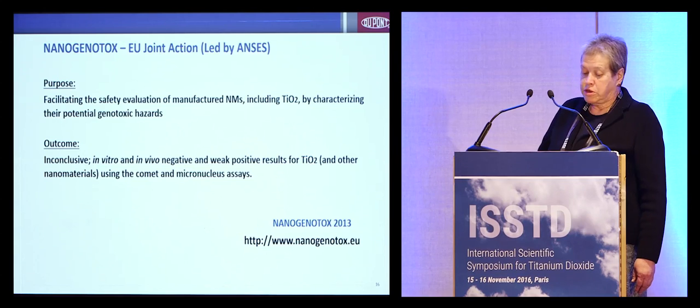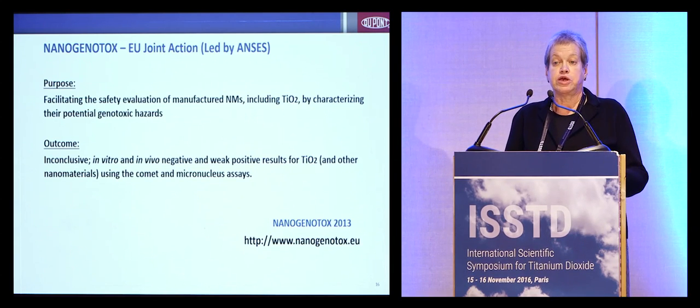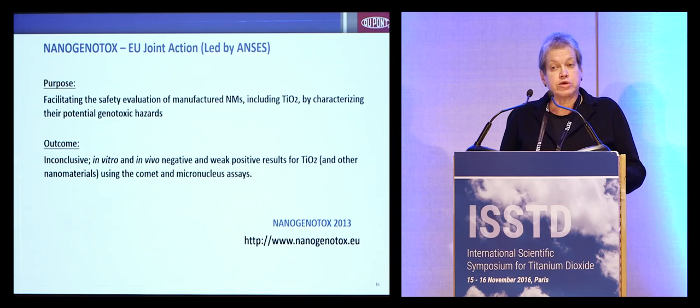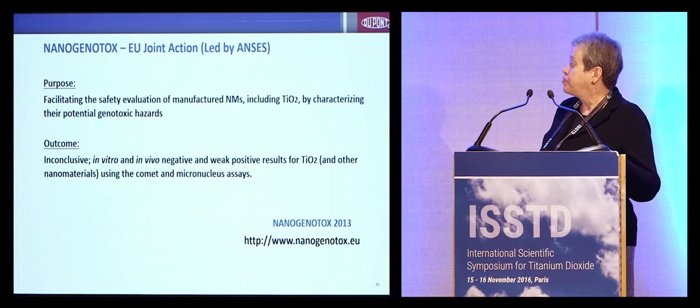There was this big NanoGenotox project, which was an EU joint action, also led by ANSES, I believe, which was published in 2013. The outcome from this one was also inconclusive in a way. There were in vitro and in vivo negative and weak positive results for TiO2 and some other nanomaterials using the COMET and the micronucleus assay. There have been many other efforts as well.